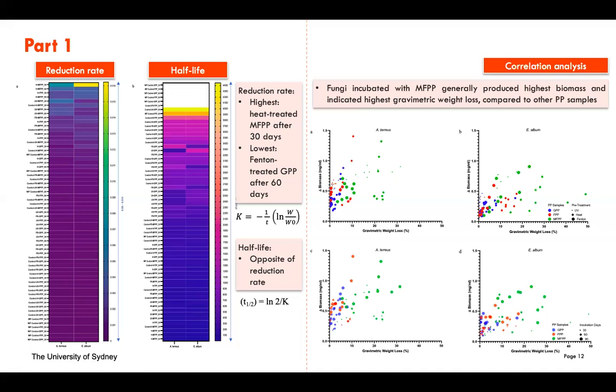And then we also did a correlation analysis to determine what are the best pretreatments that correspond to which polypropylene samples that is affected the most during the degradations. So here we can see that a metallized film will generally produce the highest biomass and indicated the highest weight loss compared to other polypropylene samples. So you can see the highest, the green one here, the metallized film, and then they are heat treated and UV treated mostly. So those produce the highest biomass and highest weight loss. So those are what we want to see the most. Right.